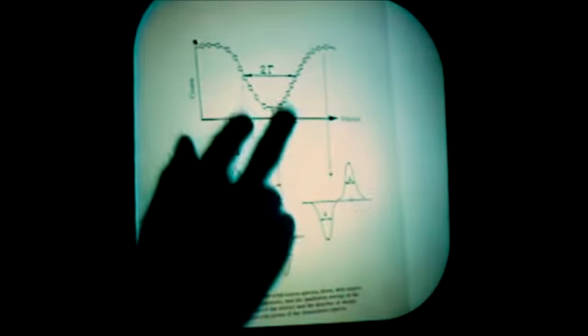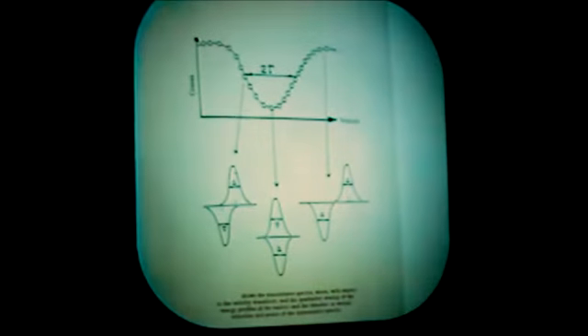And so, experimentally, you will have this resonant line, which, of course, will have a width which is twice the natural width of the photon. All of us know that the photon has a profile, and its width is the natural width. So the Mossbauer line, if you exclude all other effects, should have twice the natural line width of the photon. Okay, and definitely when you have maximum overlap, you will have maximum resonant absorption, and the number of counts will be less. So that's what we observe. And this will be a function of velocity, because your transducer is Doppler shifting the energy and modulating it, changing its value by an amount which is good enough to match the excited state you're trying to measure.